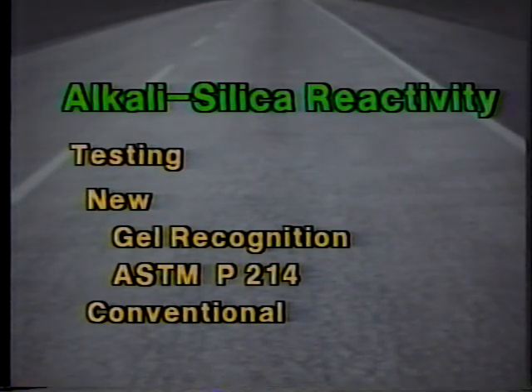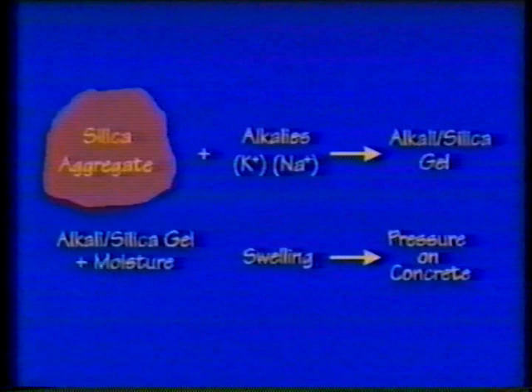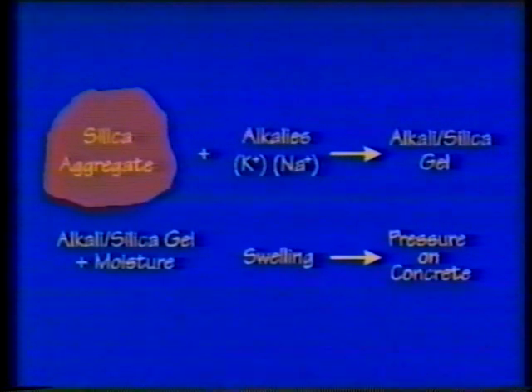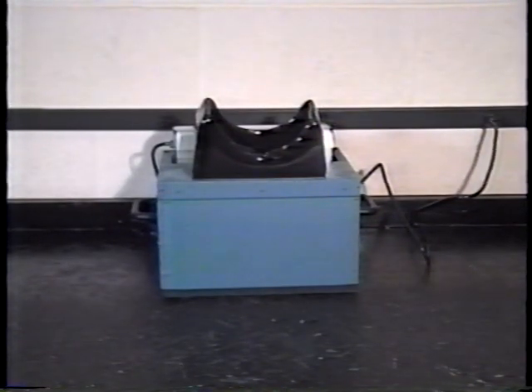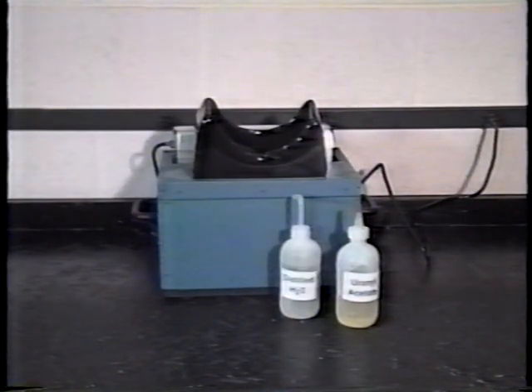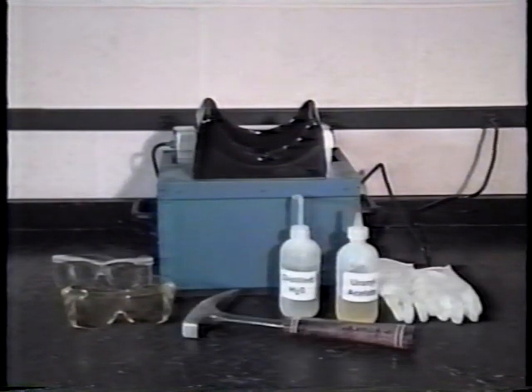We'll start with gel recognition. As indicated earlier, the presence of the ASR gel is indisputable evidence that ASR has developed. Many times this is only detectable by a skilled petrographer using a laboratory-grade microscope. But now, as a result of SHRP research, field personnel can recognize this evidence much earlier in the life of the structure. To use this method, you will need: a source of short-wavelength UV light and viewing box, uranyl acetate solution, distilled water, two types of protective eyewear — conventional and UV absorbing — rubber gloves, and a hammer or other surface preparation equipment.